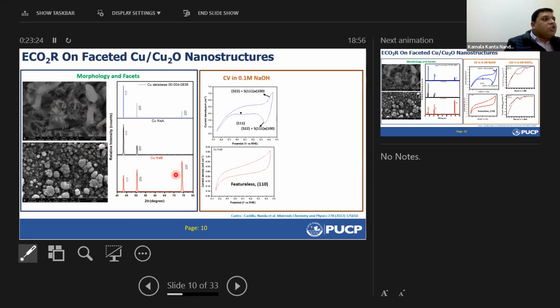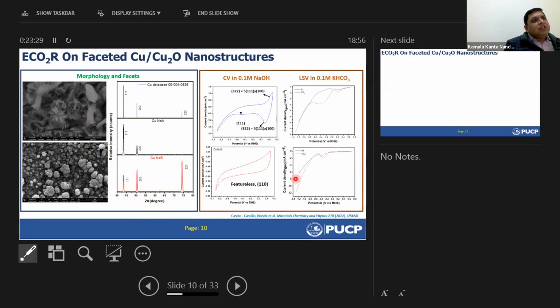We also determined the facet by electrochemical methods. The nature of facets can be revealed by linear sweep voltammetry, where if you look at the CO adsorption peak in CO2-saturated electrolyte, you have better CO adsorption on the 111 surface than on the 110 surface. So from all the electrochemical and structural characterization, we have predominantly the 1-1-1 facet in copper nanostructure A, and predominantly the 1-1-0 facet in copper nanostructure B.